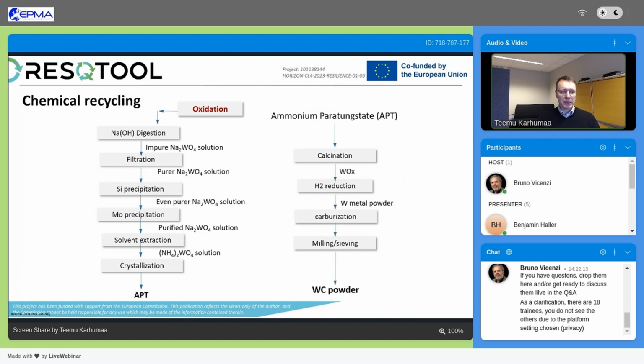And here is the process chain for chemical recycling. So first of all the tungsten has to be oxidized. In this case, this is more or less the process chain of our sister company in GTP Towanda. There is a sodium hydroxide digestion, and then out of this digestion and dissolved tungsten, there are multiple purification steps, different steps for different elements. And at the end of the hydrometallurgical process, there is a solvent extraction to change from sodium to ammonium, and then at the end of that, crystallization to ammonium paratungstate,